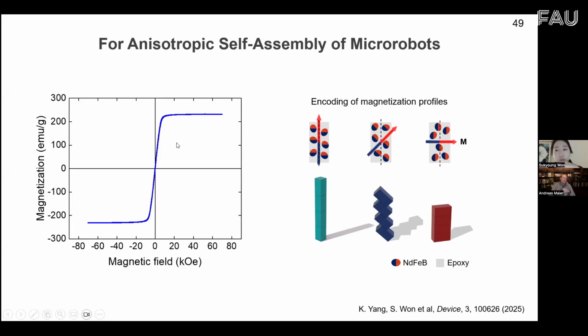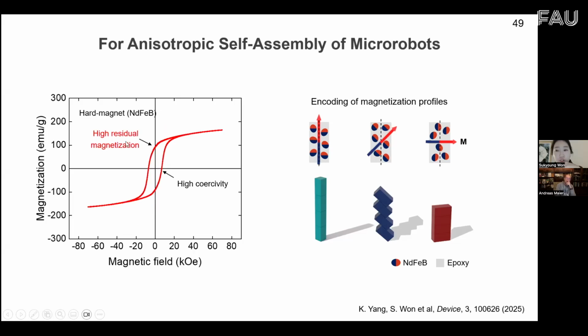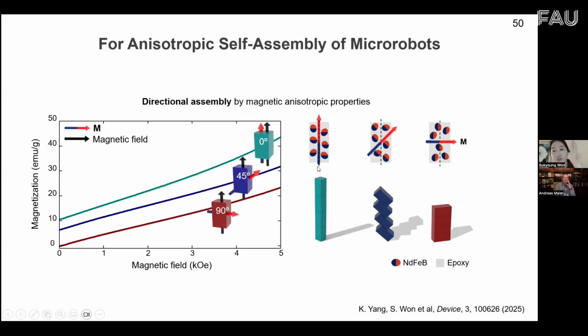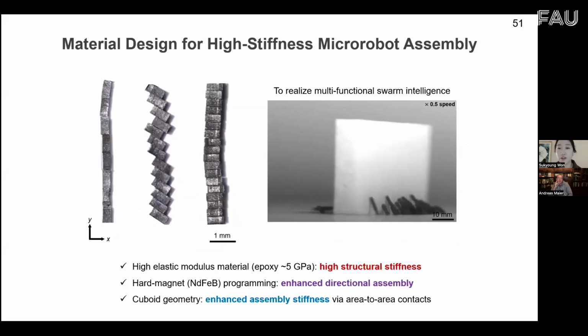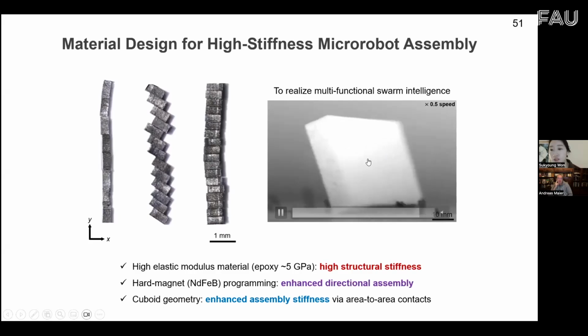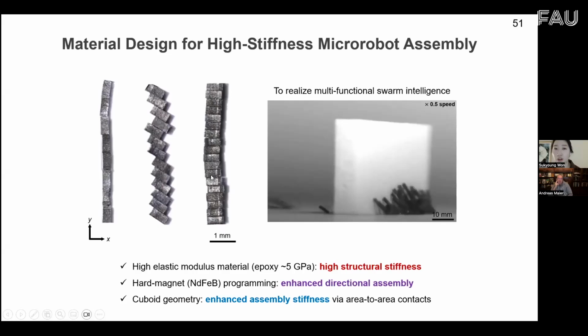Previously, we used the soft magnet, which means low coercivity with a low residual magnetization. However, when we use this hard magnet showing high coercivity with high residual magnetization, such as neodymium microparticles, we can encode this magnetization direction inside the robot body. So depending on the magnetization direction, we can program the assembly configurations, and also this magnetic anisotropic property of the microrobots shows directional swarming behavior even in a dynamic state. However, to realize this multifunctional swarm intelligence, such as obstacle overcoming, we need a high stiffness of the microrobot assemblies.